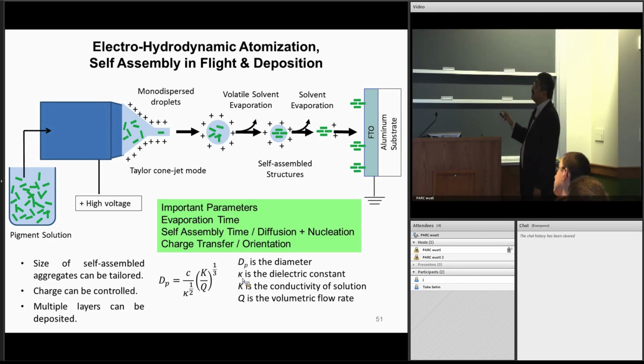So the evaporation time is important. Again, the characteristic time comparisons are so critical of different kinds, which allow us to design these processes. The droplet size is critical, and this is an equation for the droplet size, because eventually I want to create droplets of known size, but then I want to control the evaporation time, the self-assembly time.